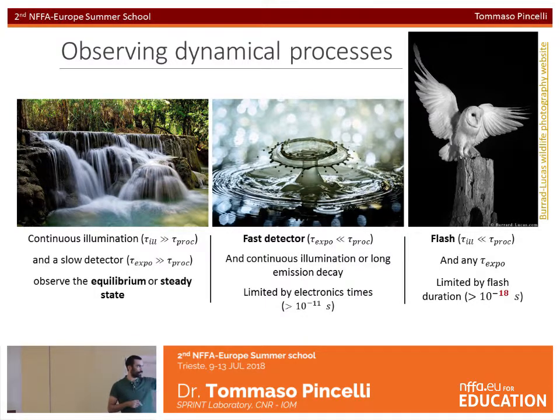To freeze a dynamical process, we can use two approaches. Either a fast detector, so the time that is required for the detector to observe the process is shorter than the process itself, and we can use either continuous illumination or pulsed illumination and look at a long decay.